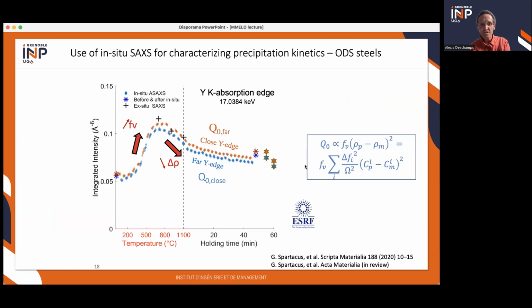And this, you can try to do in situ during an experiment. So then you can have chemical information in addition to the structural information continuously during a heat treatment. So here, for these oxide particles, it's the heating to 1100 degrees and then holding time isothermal. And you see that the integrated intensity, which is basically the product of the volume fraction times the square of the electronic density difference between precipitate and matrix, so it includes both how many precipitates you have and the contrast between these precipitates and their surroundings, increases due to volume fraction increase and then decreases necessarily because of a change of contrast.